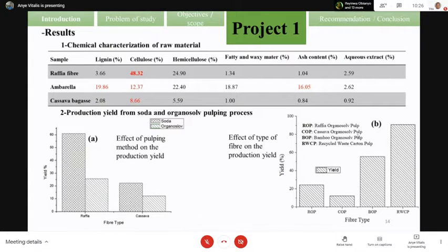So at the start of the process, we have to know the chemical composition of our raw material to choose which type of pulping process to use. With raffia, we realize it has a high amount of cellulose and a low amount of lignin, which shows it can easily be pulped with just soda pulping. Ambarella fibre has a high amount of lignin and a low amount of cellulose, which shows it will be difficult to produce cellulose pulp from this raw material. Cassava bagasse has a low amount of lignin and also a low amount of cellulose, which shows that the production yield can be very low for economic purposes.